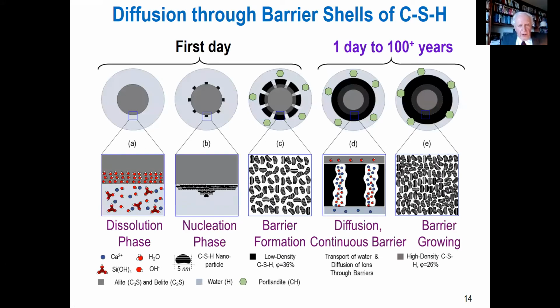Next, we need to address hydration, because that controls what happens over a long time, actually over a century, and that needs to be computed. There exists a well-known, highly regarded model of Garboczi, which models hydration through a system of thousands of cement grains of some micrometer dimensions as they hydrate. It's a very good program, but it takes a long time to calculate. It's a major calculation, and it cannot, for example, be used in fundamental programs at each integration point and each time of integration. We found at Northwestern a model which achieves nearly the same accuracy, modeling a continuum point under certain assumptions for what is happening in the microstructure.